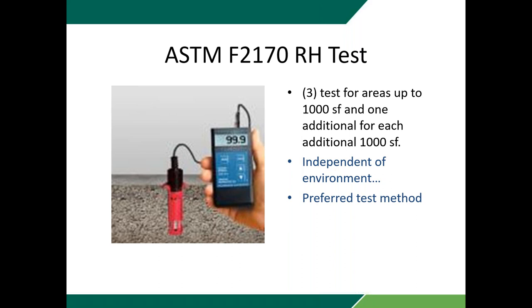I can use a calcium chloride test and I can measure a slab, and I may not get in excess of 3 pounds per thousand square foot of moisture drive, depending on the atmosphere in the room or in that little bubble that I'm putting on the slab. But even though I'm not getting that 3 pounds per thousand square foot, I may have relative humidity levels that are far above what the manufacturer's recommendations are, because in the future, that moisture could create an issue for us with a moisture sensitive coating.